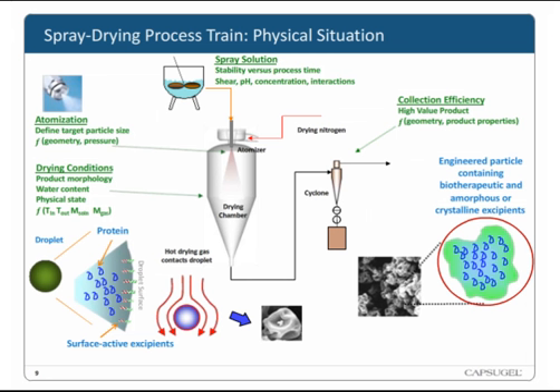And now I'd just like to take a few minutes and discuss the spray drying process as a general overview and what are the important things to think about when developing this process with respect to an inhalable dry powder formulation. And so initially we have the spray solution, which is going to be defined by the amount of solids that are present, and how we present the active to the spray solution will oftentimes determine how it's going to be in the final formulation. So if we dissolve the active in the spray solution, most often that means that we're going to have an amorphous form of the active in the final dry powder. But as I'll talk about in a couple of slides, there are other options here where we can present nano-sized active in a suspension and then spray dry that for different formulation embodiments.